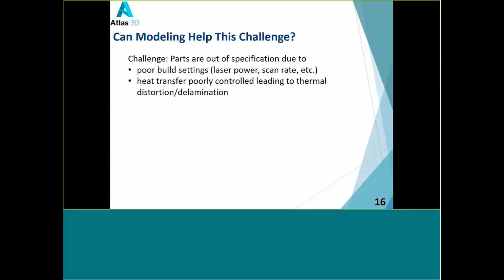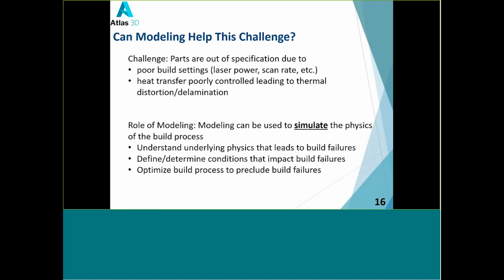We know that poor build settings, like the scanning speed of the laser or laser power, or improper control of the heat transfer, can lead to lots of thermal stress and can make the part out of specification. If we can model the whole build process, if we can simulate the physics, it helps us to understand the physics that lead to the build failure, and it will help to determine the conditions that will impact the build failure. And finally, if we can optimize the build process, all the parameters, build orientation, support structure, it will help us to preclude the build failures.